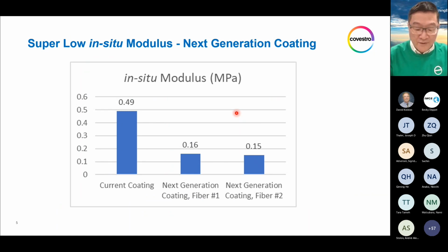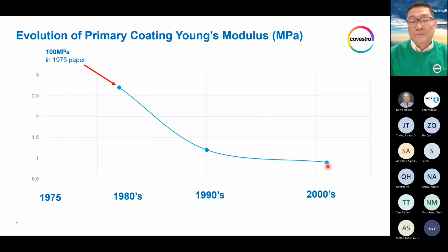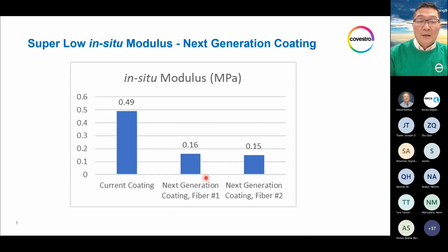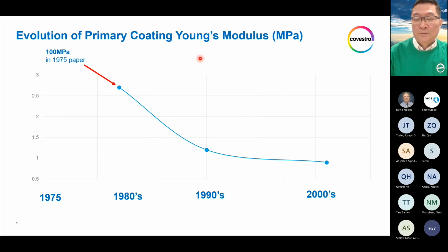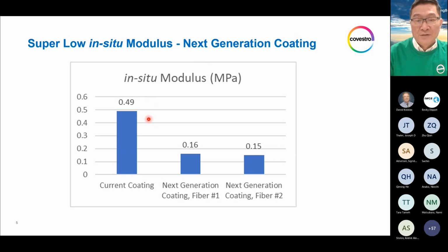So now comes the first highlight of this paper, of the current innovation. Remember, the modulus reduced from 100 megapascal to below 1, which means a 100 times reduction in about 25 to 30 years. Now I want to present the latest innovation that we have developed. The current commercial material from Covestro has an in situ modulus, which is slightly different from Young's modulus. Young's modulus is measured on the cured film, while in situ modulus is measured on the fiber directly. So this is the true primary coating modulus. It has a certain correlation with Young's modulus. So anyway, we're talking about the in situ, on-fiber modulus.